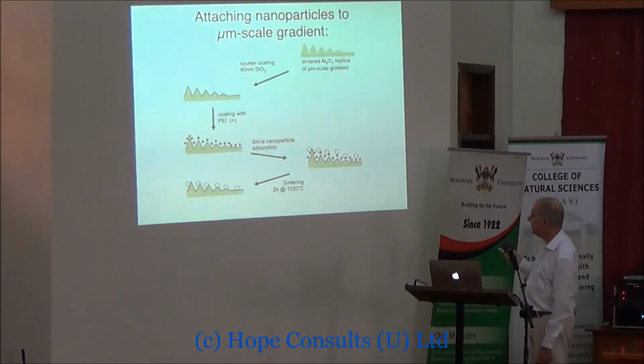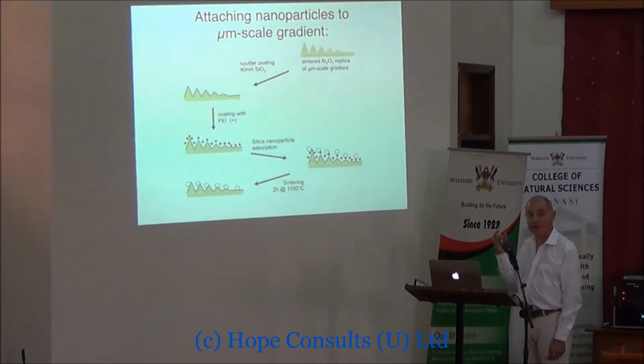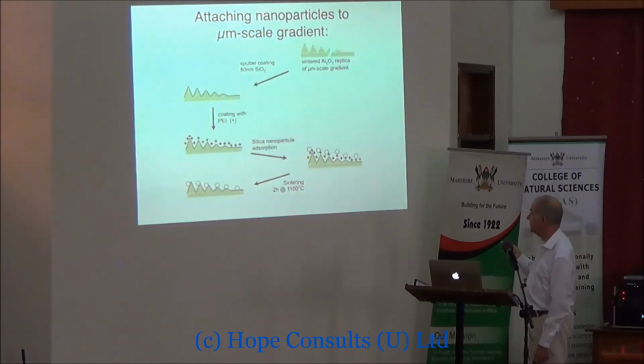So instead of using the epoxy, we used ceramic techniques. We used an alumina slurry. We made a ceramic replica of our initial negative. So we had a piece of ceramic with a roughness gradient, which wasn't exactly what we wanted. It was only the microscale roughness. So we took that, and then we covered it with silica, with sputtering.